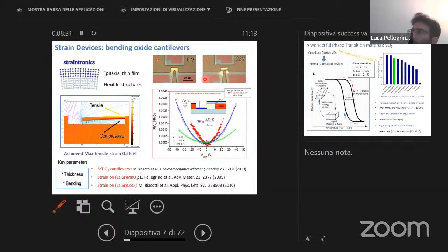At the end, we study the conduction of this structure here. And in this place, this is a cross section, but you can see here, in this place, we change the strain. We have tensile strain, and by strain, we change the distance between the ions of the cobalt oxide. So we modulate, and you can see here that we can modulate the structure at different temperature. So these devices are a way to study the conduction properties of oxides, epitaxial oxides, as a function of the strain, and we can achieve a maximum strain of 0.26%, which is quite a lot in this structure, which is about 300 nanometer thick.